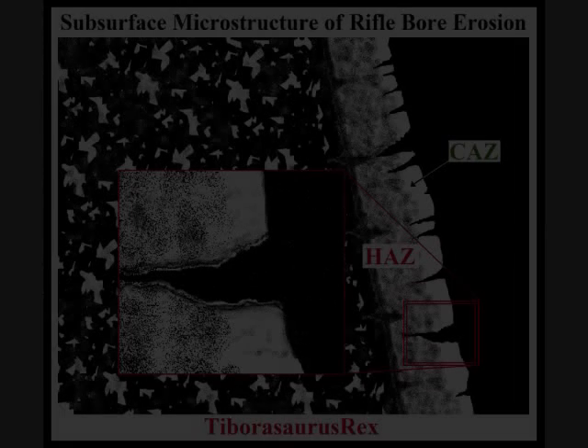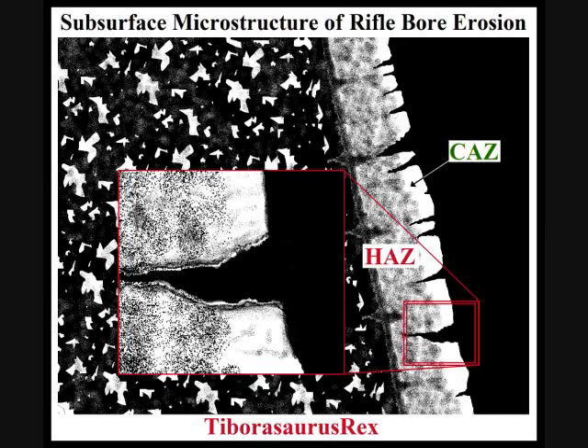So you're going to have these cracked surfaces also with the temperature zones, right? And that's going to be vulnerable to mechanical erosion and accelerates chemical attack as well. So the thermal effects are pretty dramatic. And even though at the surface you're going to have 1,500 degrees Kelvin, even 1 millimeter deep into the steel, just at the instant of the shot, you're going to have an increase up to 370 degrees Kelvin. So it's a pretty good temperature gradient from the surface of the bore to 1 millimeter of depth. So that thermally affected zone is going to be significant.